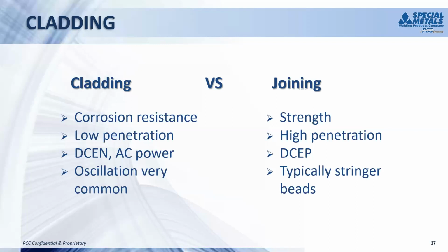You can still clad in direct polarity, or DC electrode negative. It's just that there are some advantages to using reverse polarity or AC to minimize the amount of penetration. The other difference is that when joining, you may have a slight weave or a little bit of a stringer bead. When you're cladding, it's very common to do some oscillation, so you're really spreading that weld out to get more bang for your buck, spreading that weld thin with a mechanical method versus just relying on the weld to wet out itself.